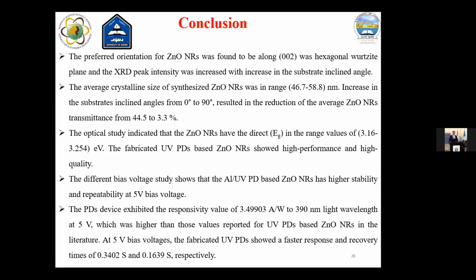The average crystalline size, which is in the range of 46 to 58 nanometers, increasing with the substrate incline angle, resulted in the reduction of the average zinc oxide nanorod transmittance from 44 to 3.3%. The optical study indicated that zinc oxide has a direct energy band gap. Lastly, the different bias voltage studies show that the UV photodetector built on the zinc oxide nanorods has higher stability and repeatability at the 5 volt bias voltage.